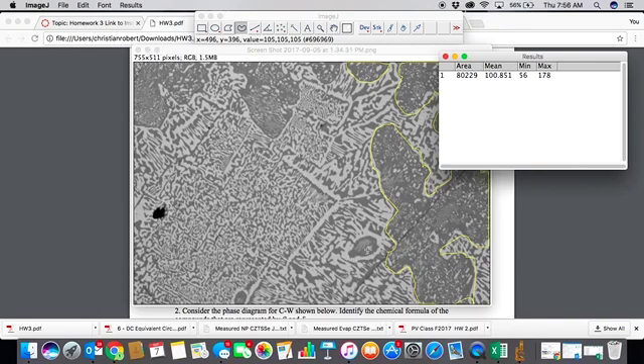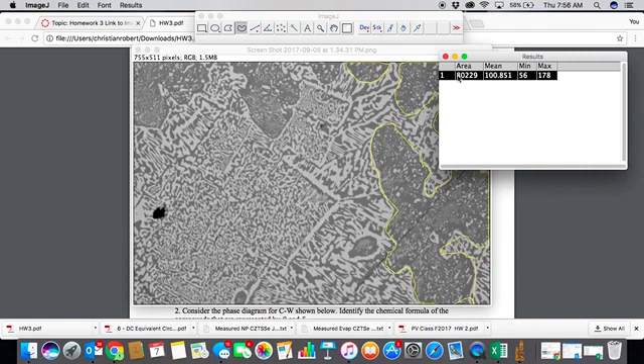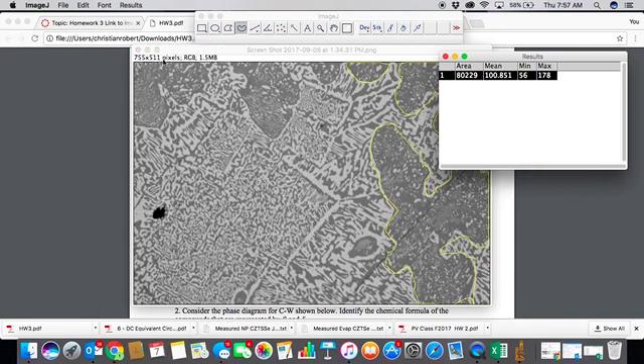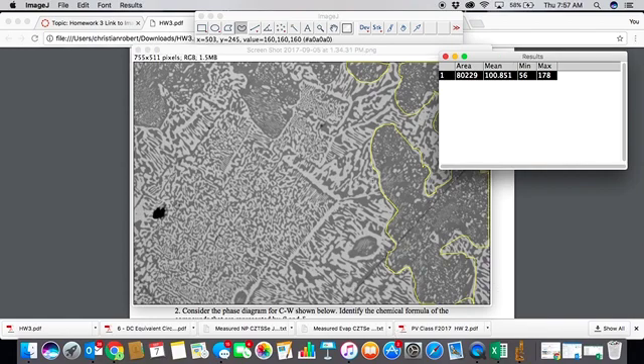And so if you had all of them selected, it would tell you exactly how many pixels of this image are pro-eutectic. Excuse me. You'll learn the difference between those. And so what you can do to find the fraction is you can take this number here, the 80,229, and divide it by the total number of pixels. And you can figure that out by just multiplying these two numbers up here on the left by each other. And that will give you the total number of pixels in the entire area. So that's one way that you could make this calculation using the lever rule. And I'll show you another one.